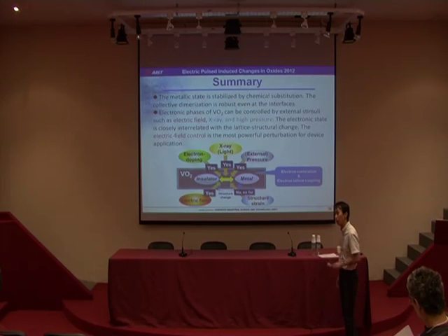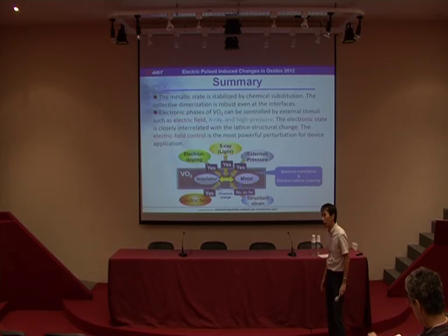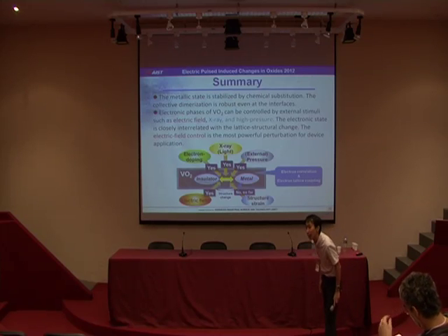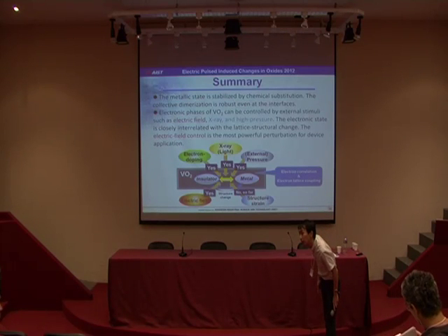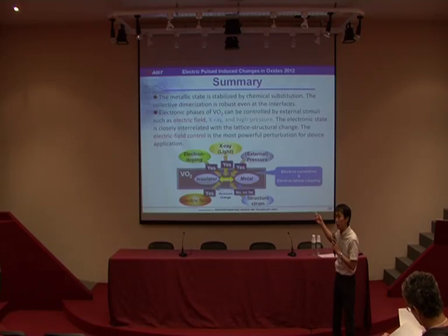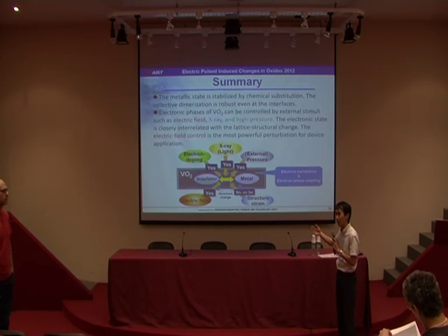Why don't you just do the magnetization? Even doing magnetization measurements, one should be able to get the susceptibility. Actually, it's difficult. This is a thin film, so it's almost impossible to measure the antiferromagnetic state in thin film.